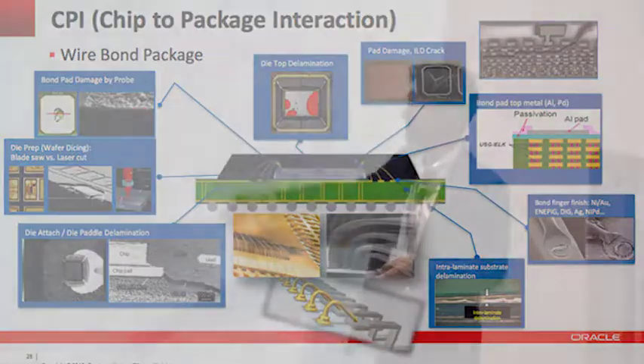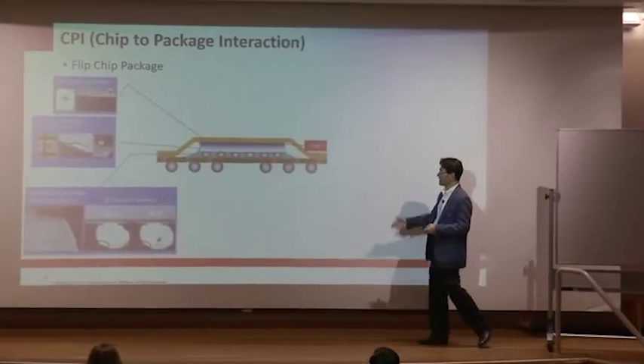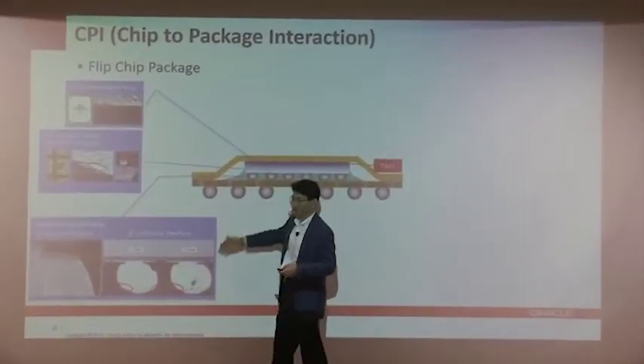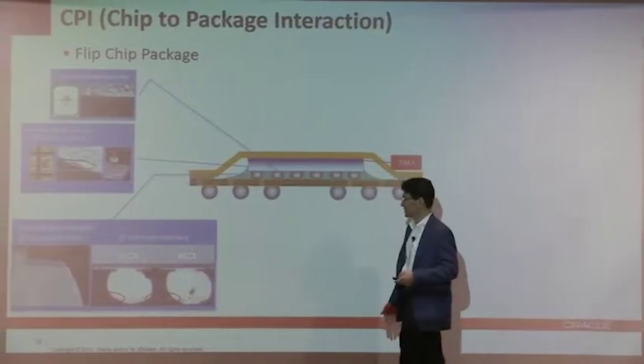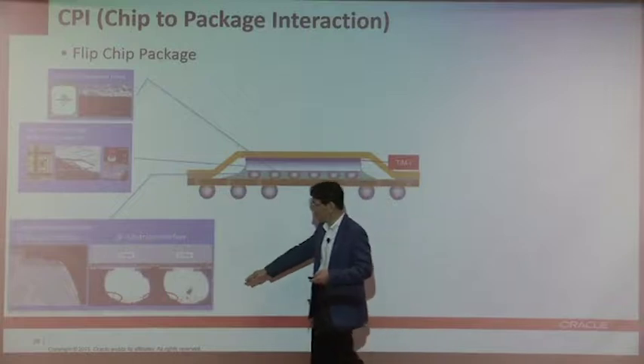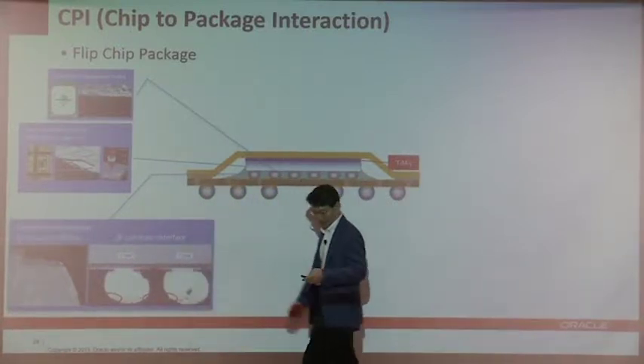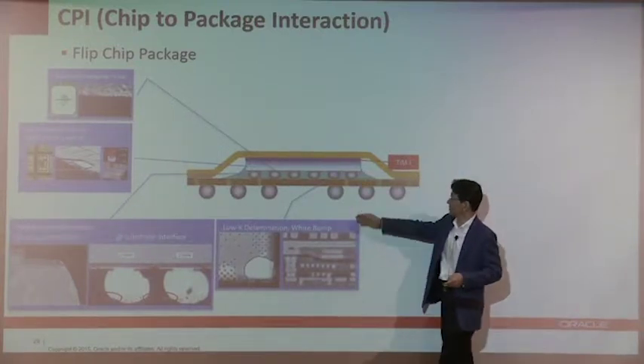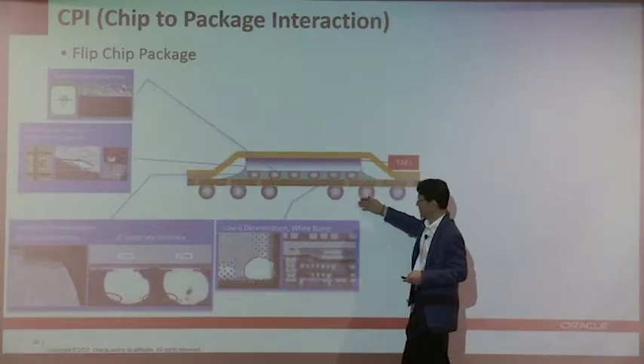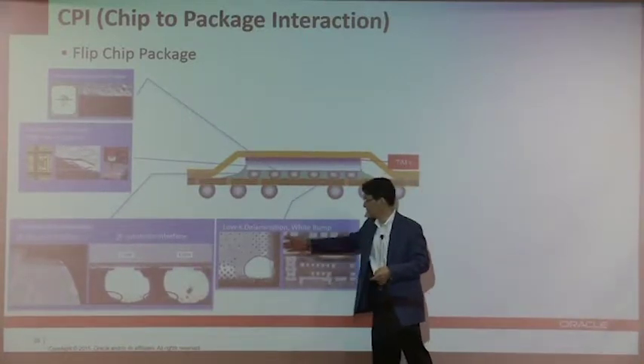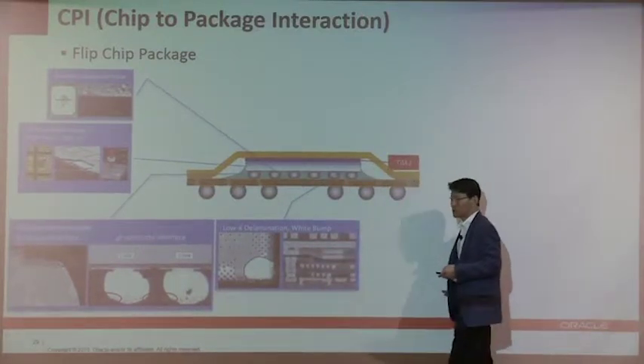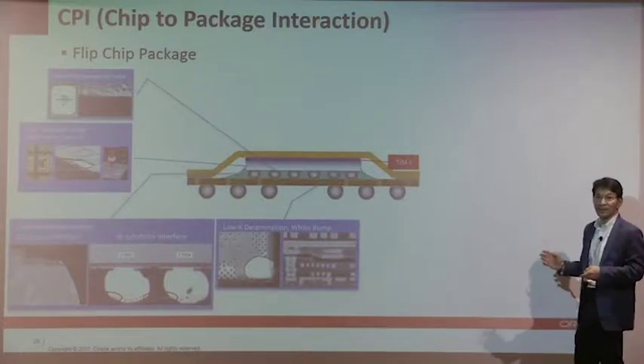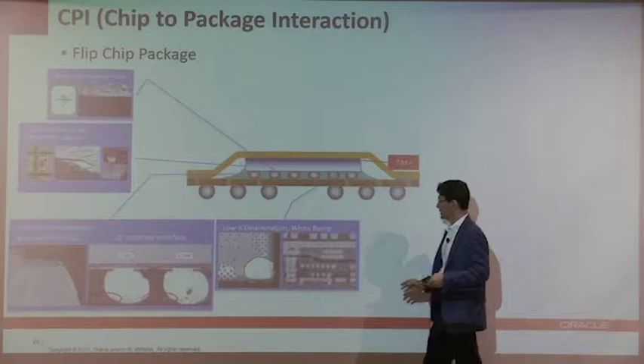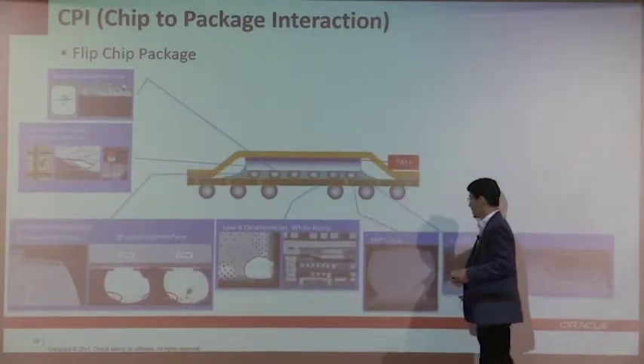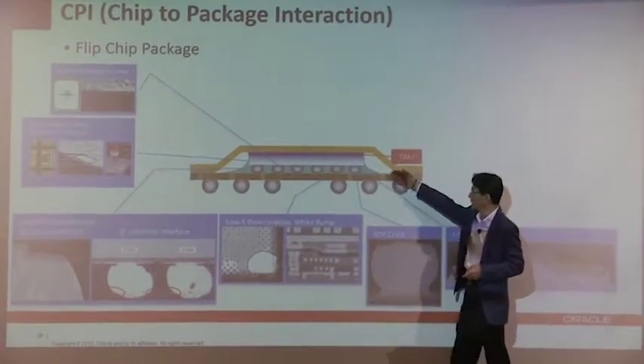Flip chip has the same kind of failures. And instead of wire bonding, it uses bumping. It has another problem: the bump crack or delamination, and the bridge between bump and bump. Also, the bump is connected to the I/O pad directly, so it has higher stress than wire bonding, and this kind of low-K area delamination, so-called white bump, has to be considered at the beginning of the design. And SOP, solder on pad crack, and UBM side crack. It's happening.